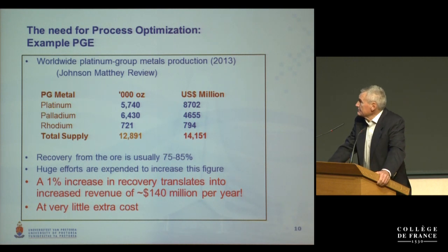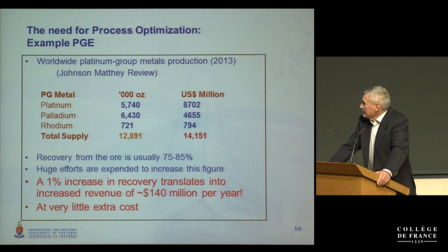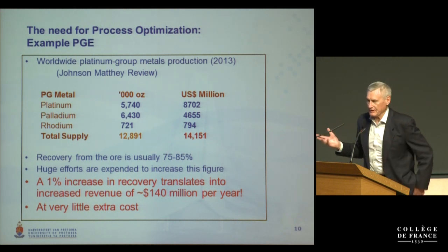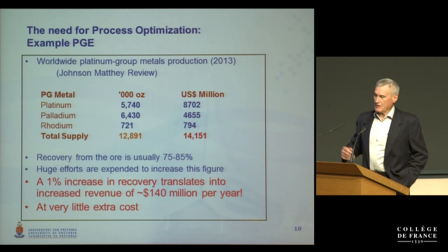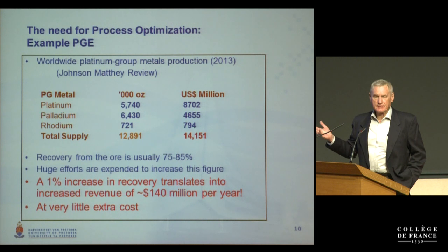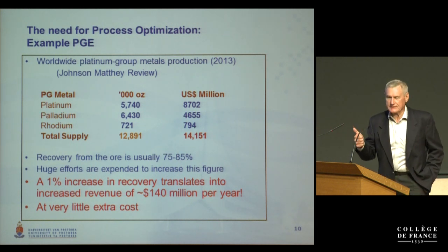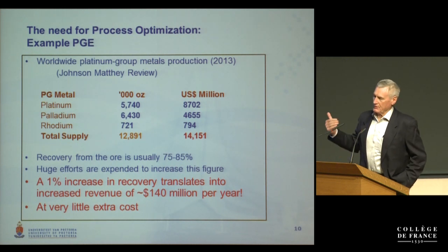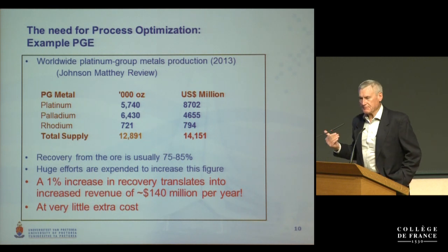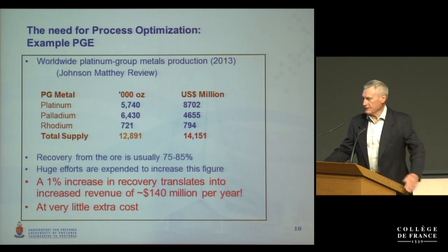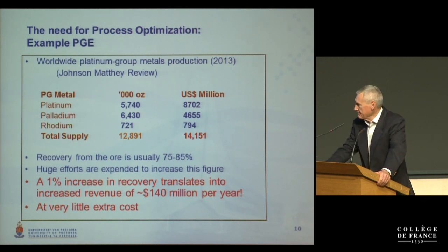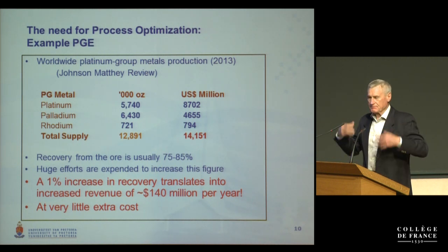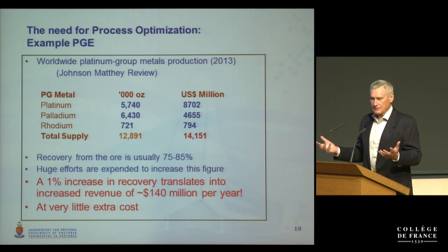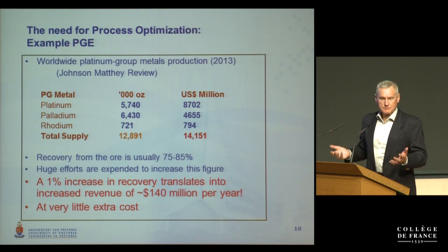In the case of platinum group metals, we see that the total supply in US dollars is $14 billion. The recovery from the ore is usually about 75 to 85%. So there is an opportunity of 15 to 25% increase in recovery. So if you have a 1% increase in recovery by optimization or better reagent choice or better milling practice or whatever, that translates to $140 million per year, 1% recovery. And this comes with very little extra cost because the plant is already operating, it's already producing. So any incremental increase is pure profit.